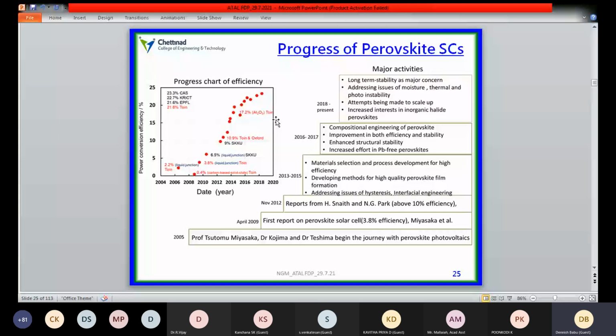People are also looking at compositional engineering of these perovskites and improvements in both efficiency and stability of these materials. And nowadays people have started to work on long-term stability, which is considered a major concern for these perovskite solar cell devices, as well as the issues of moisture, thermal, and photo instability. Those two are the main drawbacks of these perovskite devices. If we optimize those parameters, we can get some good fruitful results from these perovskite devices.